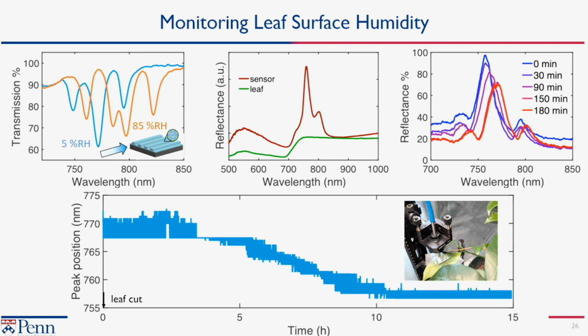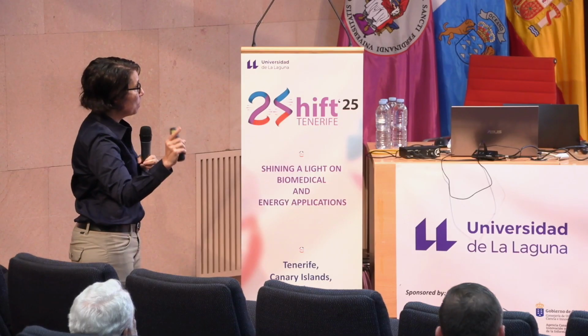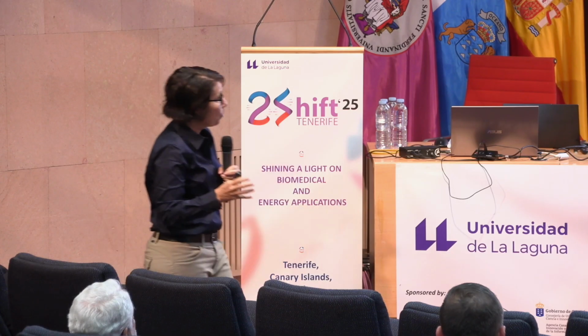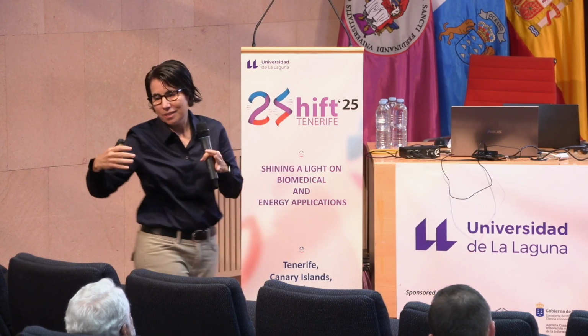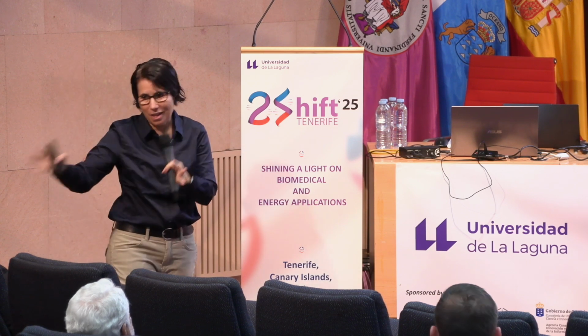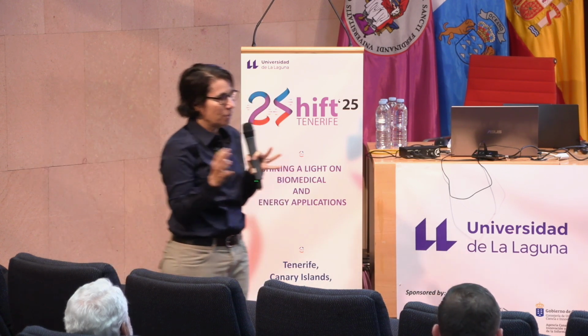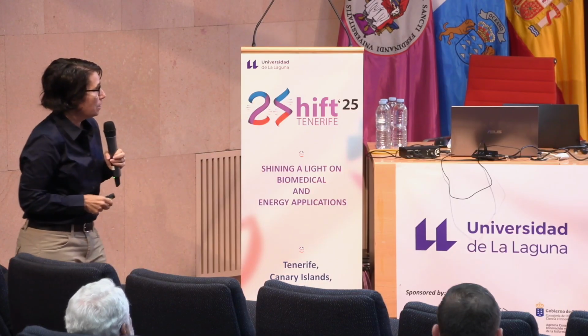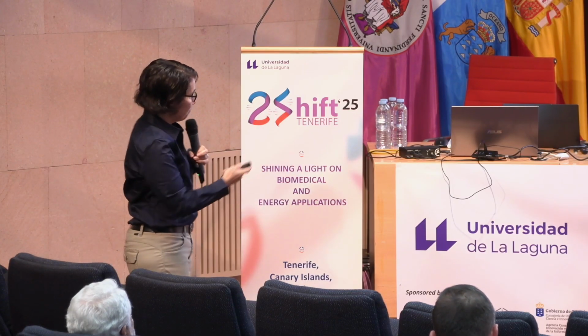And what we did as a first test is that we took a leaf, and it's now sitting at this state here. And if we cut the leaf, what happens to your leaf? It loses its water over time. You can actually characterize that by a technique called porometry. And you can watch over time as the moisture level in the leaf drops, using the sensor. And all we're doing is just doing spectroscopy and monitoring that peak over time. And so we can use it as a way to measure our techniques. And now we've deployed these to California and Indiana, and we're trying to measure these out in agricultural fields on things like corn and sorghum and some pistachio trees.